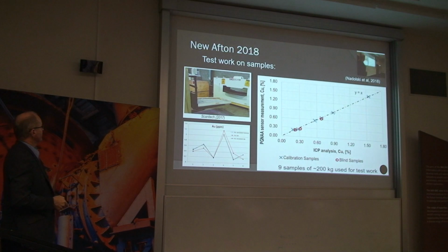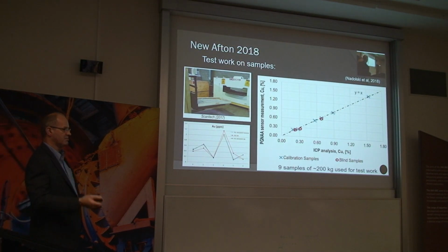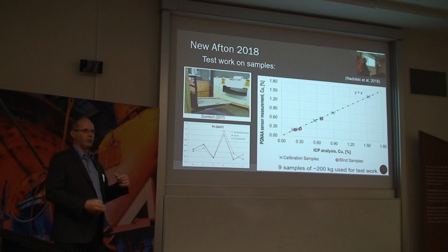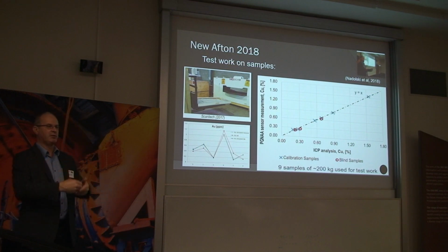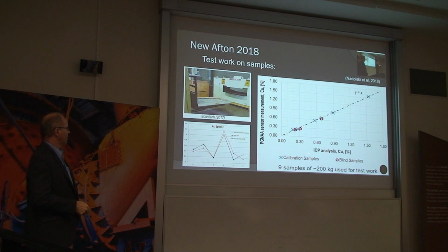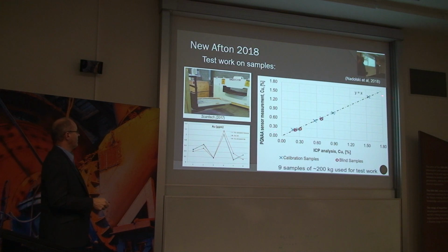So the first thing, they sent us samples to do test work. To get samples, we need the customer to crush them, sub-sample them, so that we have a lab assay to calibrate to. So we received these 6 blue crosses as calibration samples, and these 3 samples as blind samples where they didn't tell us the grade. So we set up calibration, tested the blind samples, and they were very happy with the performance.